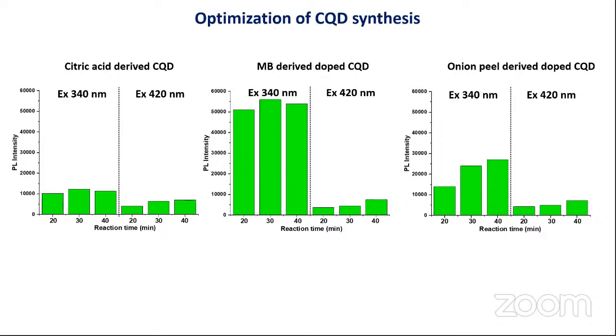So we have found that in the case of methylene blue, we are getting higher intensity. On the basis of that, in this case the 30-minute one is showing better results, and also in onion. Gaurav, you have got 1 more minute, so we have to rush.